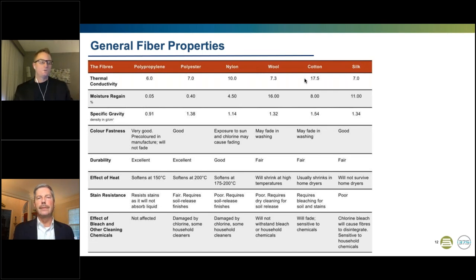When we first started, we were mainly in virgin polyester. Today, we're in recycled variants of that, nylon 6-6, nylon 6, developing polypropylene, et cetera. One of the things I'd like to touch on is how important the master batch is to the success of that, in order to deliver our brand promise to our consumer brands. When we get that master batch COA with the loading, the dispersion, the indications around melt index and viscosity — all of those are incredibly important to us so that we can achieve high yields at different manufacturers around the world.